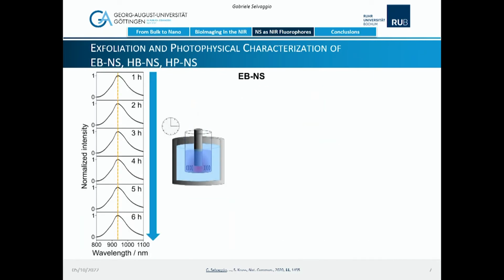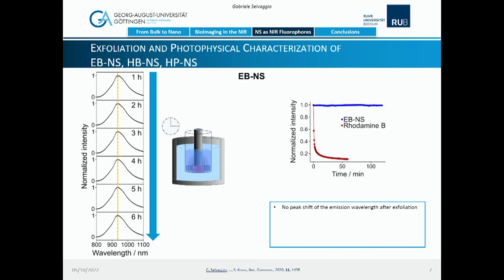If you remember, this was the first voice of this challenges red box. And you see here, by increasing tip sonication time, and therefore yielding smaller and smaller nanosheets, you don't get any difference in the emission profile, meaning that you don't get any peak shift at all of the emission wavelength. Furthermore, photobleaching is not happening in the case of Egyptian blue. This is a typical phenomenon mostly occurring for organic fluorophores. And you see here, you can image nanosheets of Egyptian blue for up to 2 hours without any significant difference in the intensity. And this, together with the previous dataset, really highlights the high photostability of these materials as novel near-infrared fluorophores.